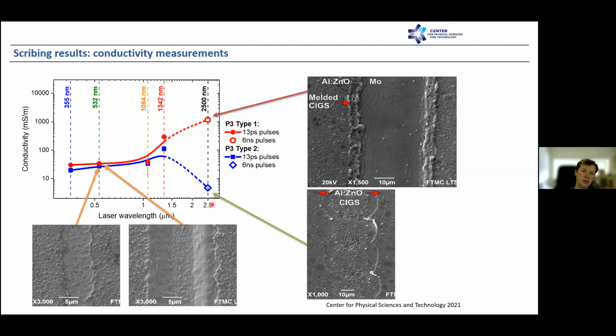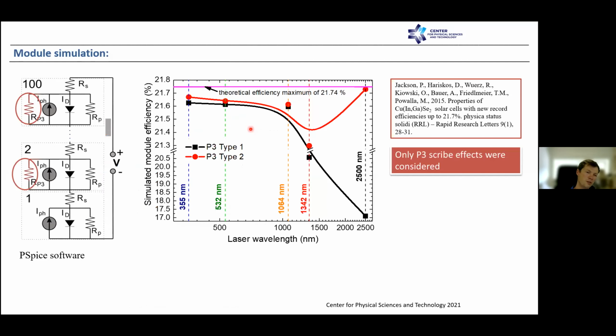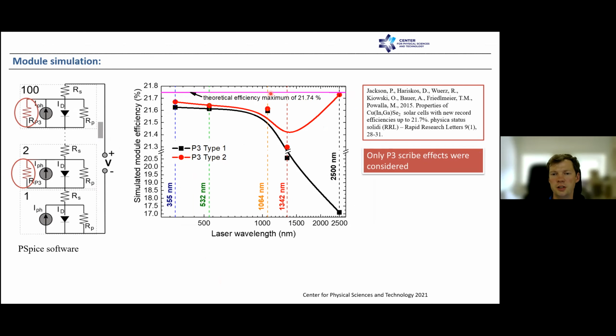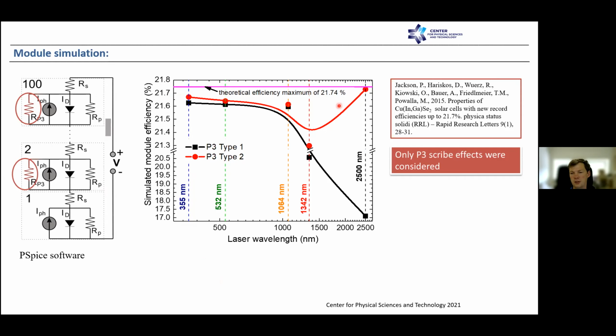So as we obtain these specific scribe conductivity values, we can then model our module performance, taking into account these additional parallel resistances caused by the laser scribe. We use PSpice software for module simulation up to 100 cells, and we see some results for the simulated efficiency of a module. Here we have a theoretical maximum efficiency of 21.74%. It means that we took some values for the modeling from one article, and we see that, of course, after 100 cells we have some degradation of efficiency, because in any case we induce some parallel resistances.